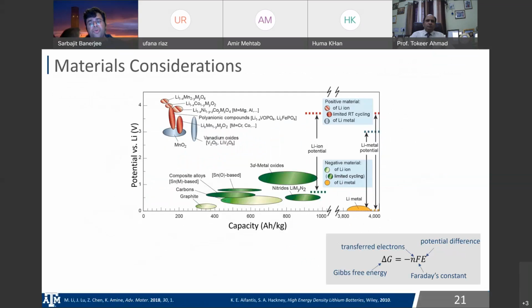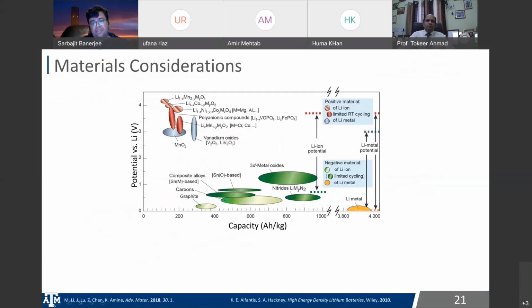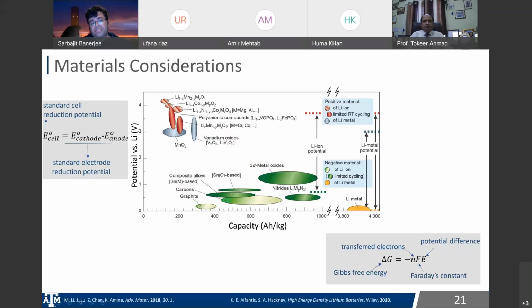This is a view of some materials considerations, right? So on the one hand, you care about potential. This is something that you learn about in your electrochemical series, right? Your lowest potential here is lithium metal, and you've got graphite here, right? And you've got these transition metal oxides at higher potentials. And so essentially your cell potential is the half cell potential of the cathode minus the half cell potential of the anode, right? So if you want to have a larger voltage for your battery, you want to pick something as high as possible as your cathode and as low as possible as your anode.